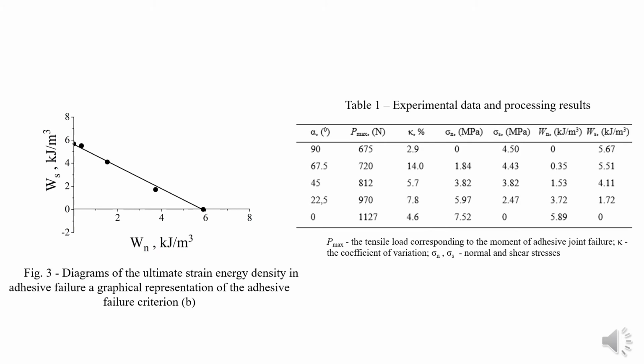Table 1 shows the experimental values of the failure load for each angle alpha and the coefficients of variation. It is assumed in statistics that the degree of data dispersion is considered to be insignificant if the coefficient of variation is below 10%. It is obvious that for most of the angles, the data dispersion is insignificant, this being indicative of experimental data repeatability. Therefore, it is possible to speak about the repeatability of the experimental data and about the applicability of Arcan specimens.